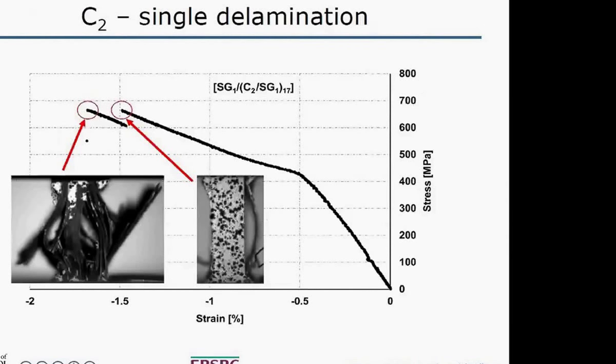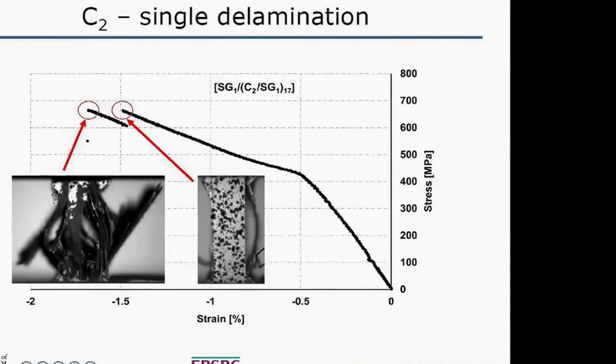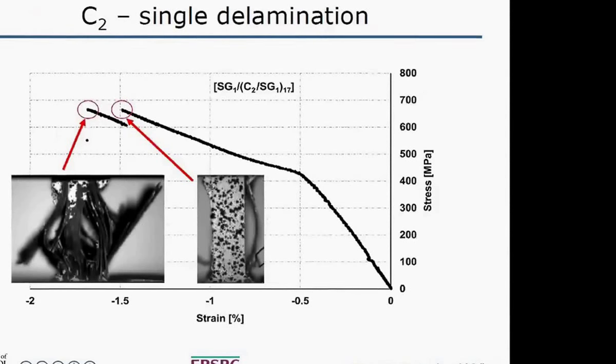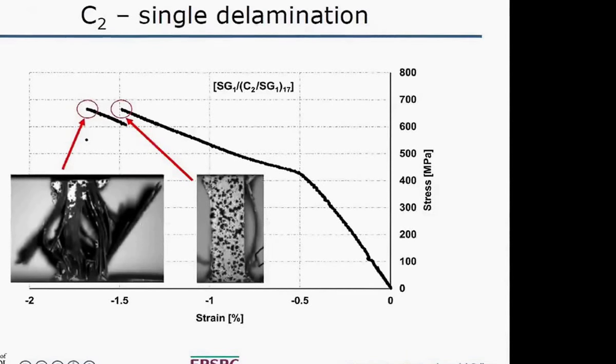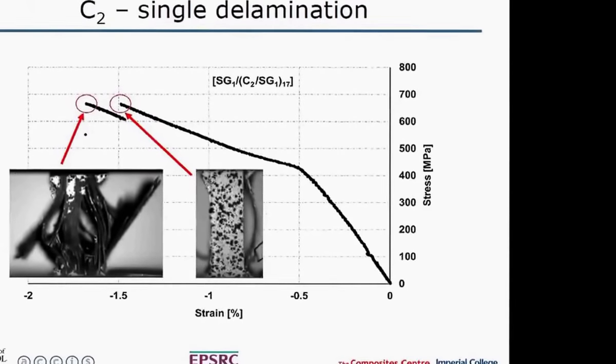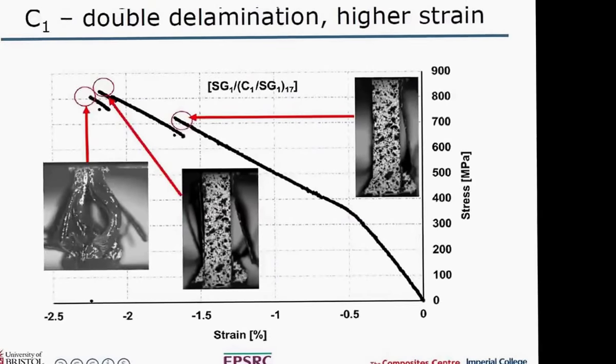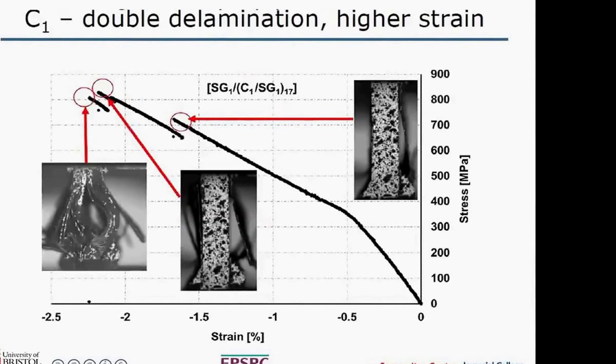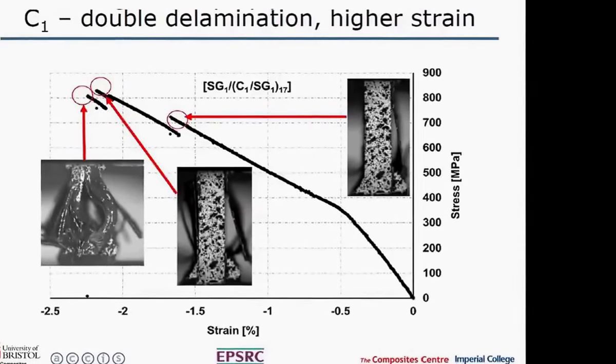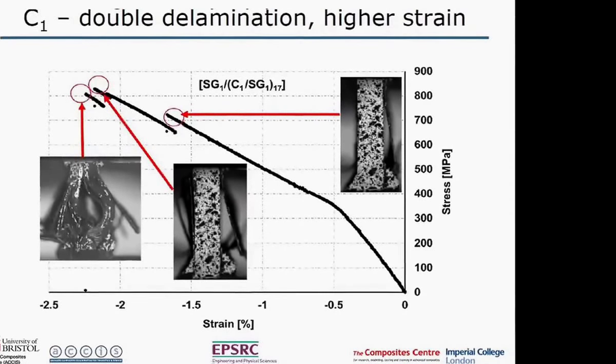And then at this point here, we get a load drop, and that is actually the surface glass and carbon ply delaminating. And then it goes a little bit further, and then the whole thing fails catastrophically at this higher strain. And if we go to the single carbon block, then we have the same trend. We have first one load drop here, then we get a second load drop here, where the other side delaminates on the surface, and then we get this catastrophic failure shortly afterwards.